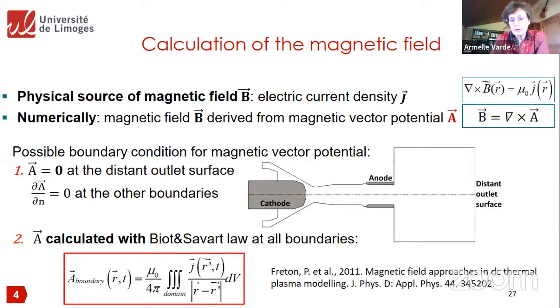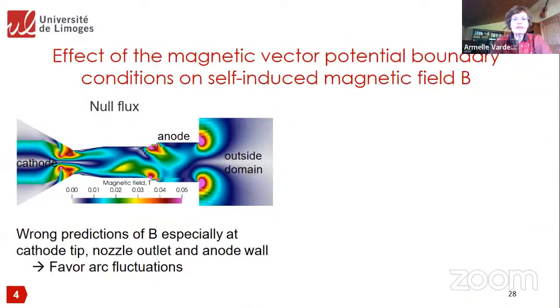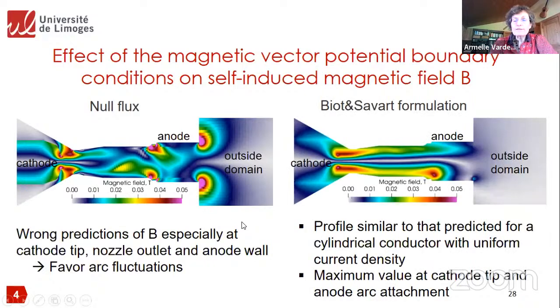You have surely seen this law in your previous studies. Now, just look at the difference of results we can get when we change these boundary conditions. Here, we have used the null flux on all the boundaries. And when you look at the field you get, it seems that it's not so good. It's very strange. You can see that especially at the cathode tip, at the nozzle outlet and the anode wall, they look wrong. While if you look at the prediction we get now, when you use the Biot-Savart formulation for the boundary conditions, you get what you are expecting.